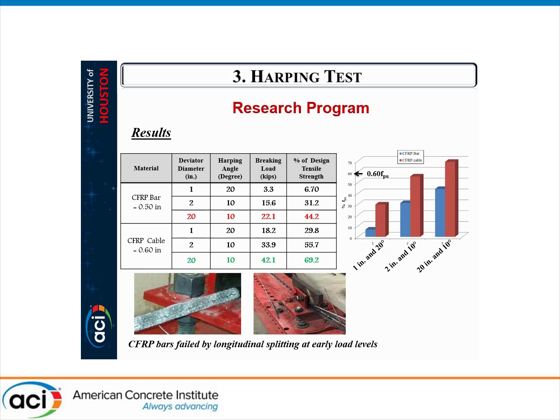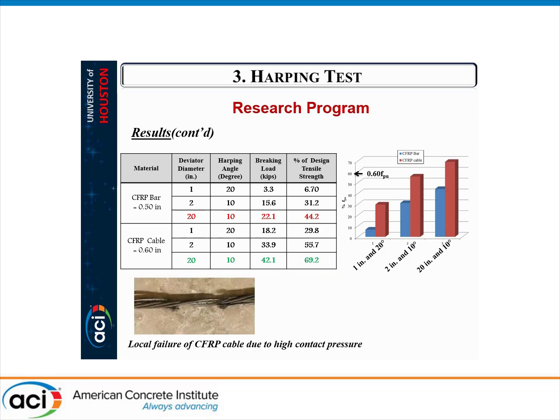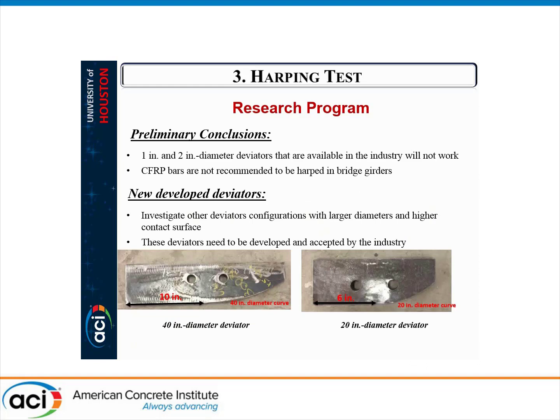In the case of CFRP bars, we have splitting cracks, as you can see here, which end up in failure at a very small load. And in the case of CFRP cables, we have local failure of the wires. So our preliminary conclusion was that 1 inch and 2 inch diameter deviators that are used for steel prestressing are not suitable to be used for CFRP. And we also recommended not to use CFRP bars in bridge girders due to the range of harping angle that is required there.